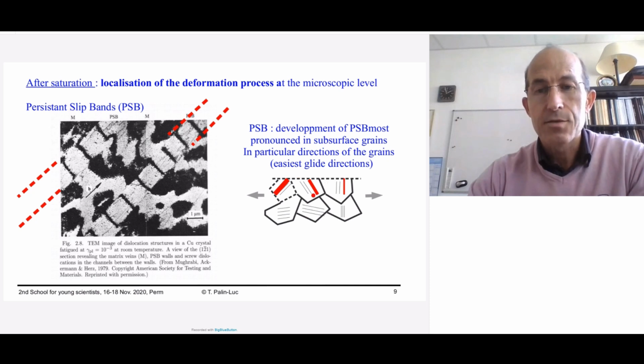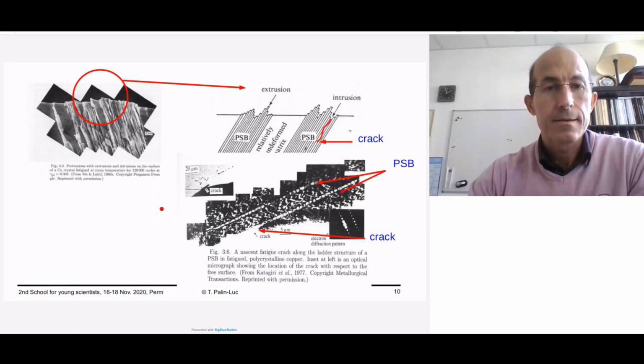In the grain, the red lines illustrate the veins or the channels of dislocation movement. And these dislocations emerge at the surface and will create persistent slip bands which appear at the surface. So these bands are orientated along the directions of the easiest glide directions. You can see here an illustration of such bands. Here you can see the surface of the material and the appearance of extrusions, which are schematically illustrated here with the PSB and the extrusion.